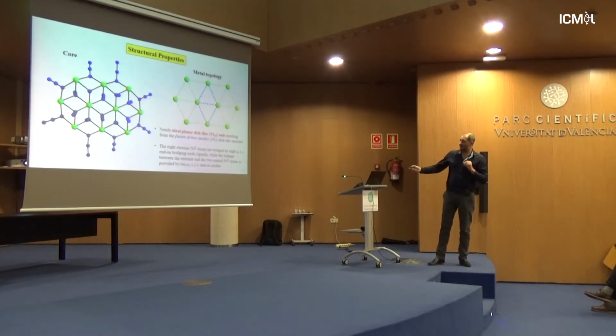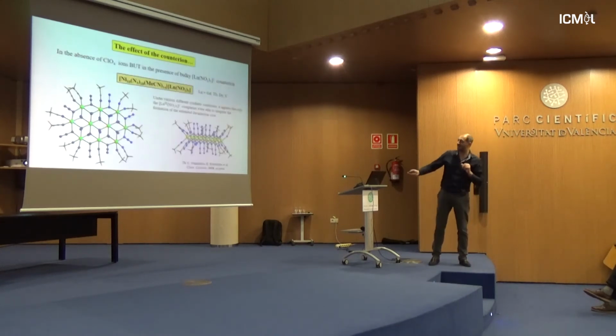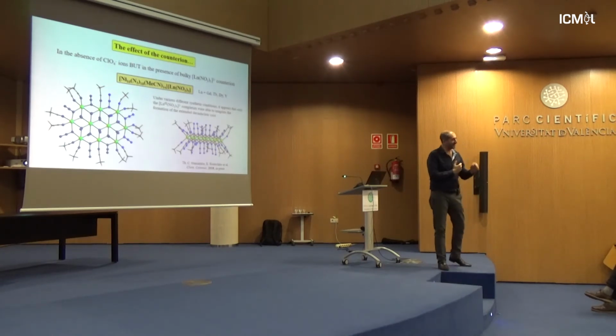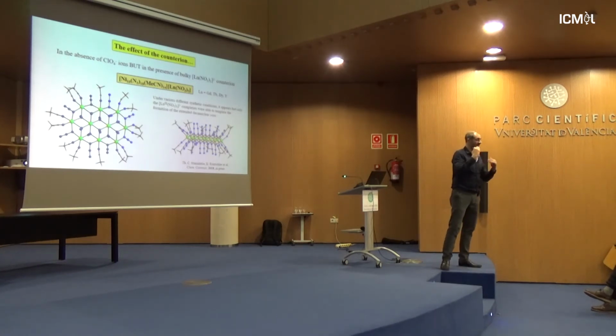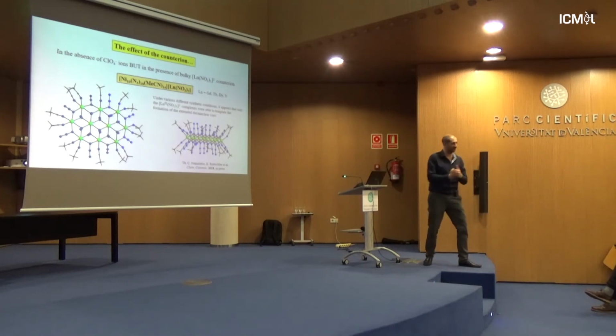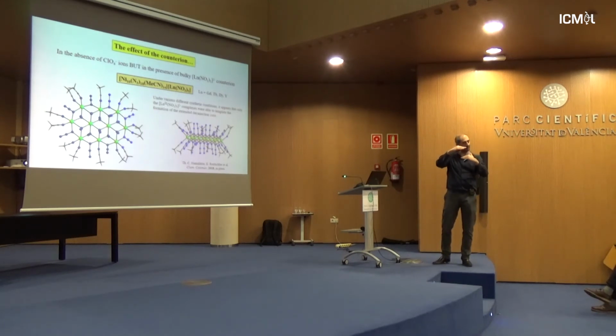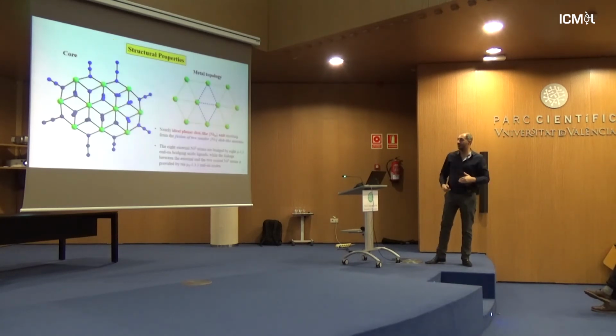This is the core, the metal topology. Again, we have only bridging azides. The terminal sites here are occupied by terminal acetonitrile molecules. We still see solvation-desolvation effects. You see that the crystals change at room temperature. Thank God we don't need to put those crystals under a glovebox because nickel cannot get oxidized. It's always stable in the 2+ oxidation state. And we were able to figure out how the crystal degrades with time.